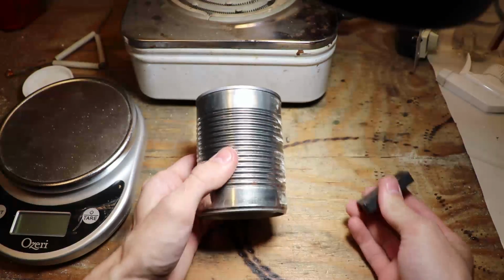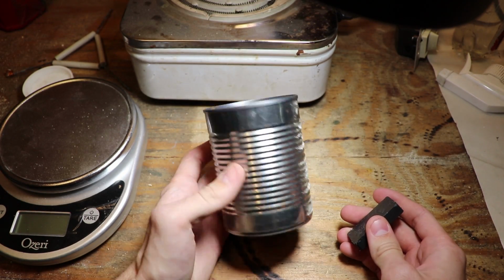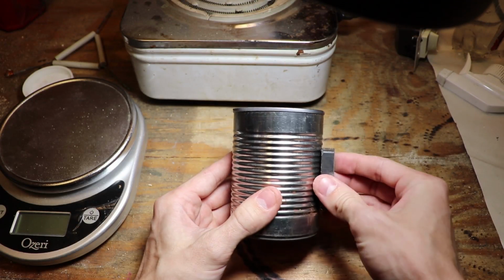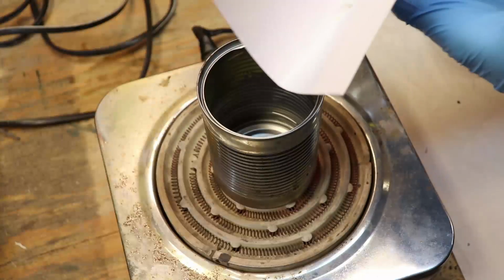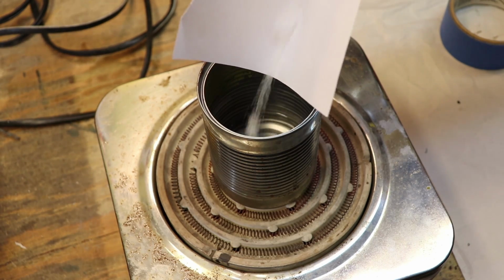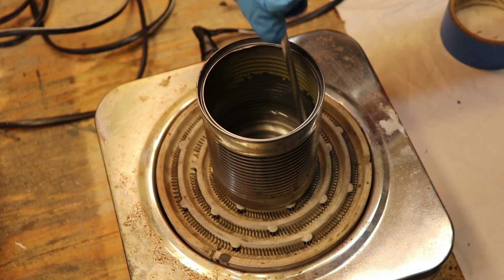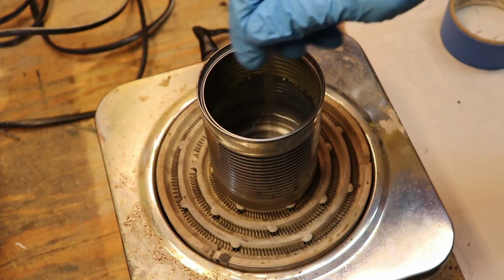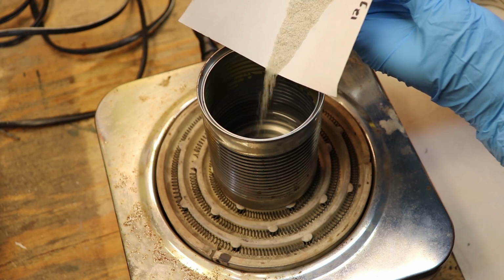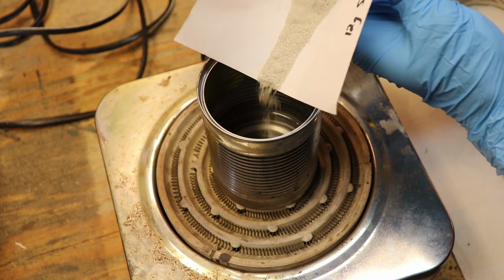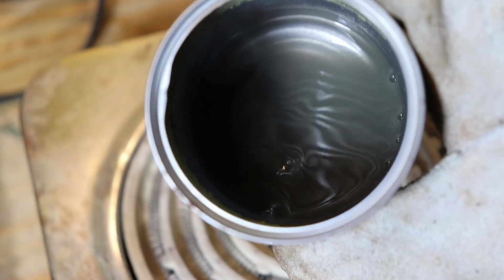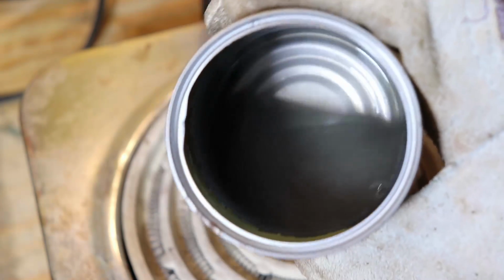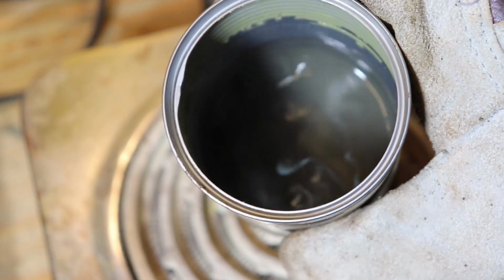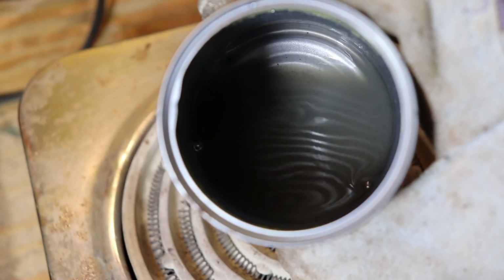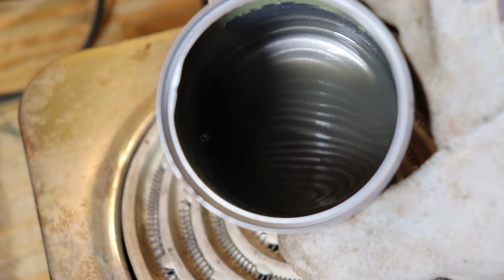Now, I'm using a steel container for this. Anything aluminum will get eaten by the lye, and we don't want that. So first I made sure my water was warm, then added the lye and stirred till it was completely dissolved. And then I added the silica and stirred till it was completely dissolved too. Now we have this dark watery mixture, which is fine. I mixed a lot of different silica beads together, so that's probably why I'm not getting a clear solution.